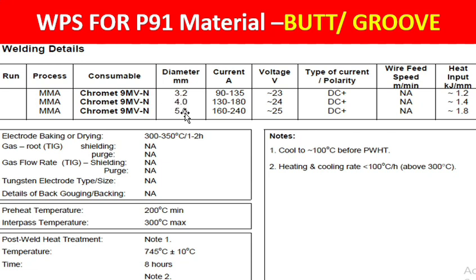Current is 90 to 135, 130 to 180 for 4.0, and for 5.0 diameter it is 160 to 240 amperes. Voltage is 23, 24 and 25. Current polarity is DC positive. Heat input is 1.2 kilojoules, 1.4 and 1.8. There is no root, that's why the current polarity is DC positive. Electrode baking is required: 300 to 350 degrees centigrade for 1 to 2 hours. There is no root, and there is no tungsten electrode.